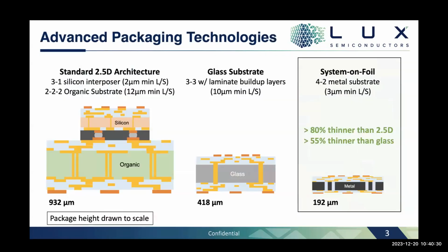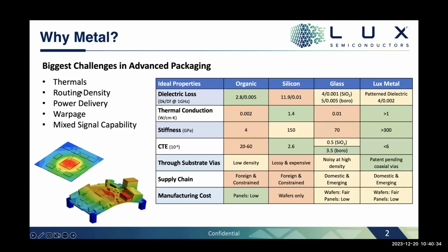Yeah, okay. So going back up here, what you get with this is a substrate that has significantly higher thermal conductivity than your organic materials. So that's pretty big. Silicon interposer, silicon is also high, relatively speaking, than organic and glass. However, as far as we're aware, all silicon interposers are mounted to organic substrates. And so there's still that bottleneck, at least getting thermals down out of the package. Now you can do the thermal solutions on top of the chips, of course, but this basically provides you a built-in heat sink. That would be one.